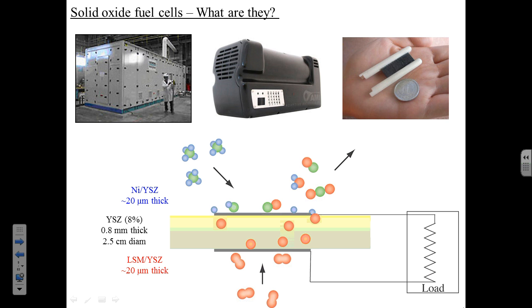They produce electricity. Depending on the fuel that goes in, they will produce products, carbon dioxide, water. They come in sizes as large as 250 kilowatts. This is a stack by Siemens Westinghouse. It operated for 10,000 continuous hours powering a couple of small towns in the Netherlands. This is a 50-watt unit from Adaptive Materials. And then this is a 2-watt micro-solid oxide fuel cell that was just produced in Japan. The solid oxide fuel cell has three ingredients to it: an anode, a cathode, and a solid oxide electrolyte, hence the name.